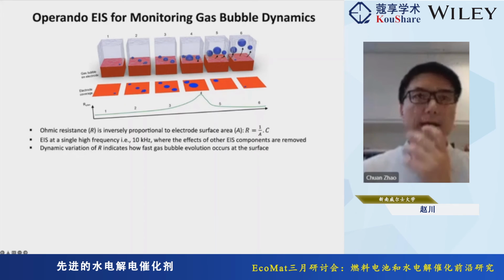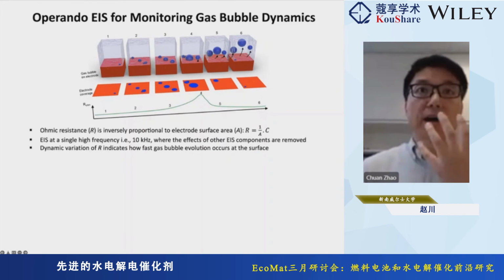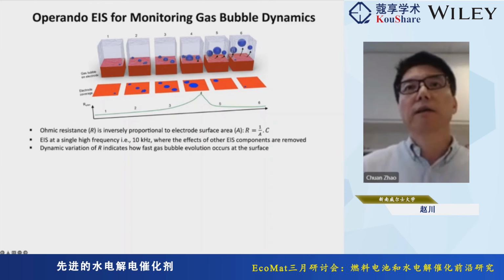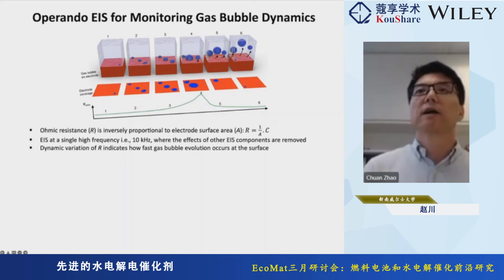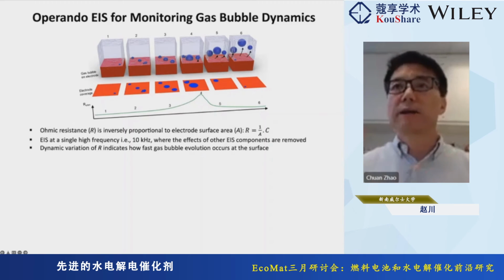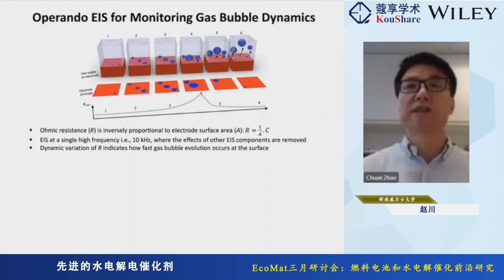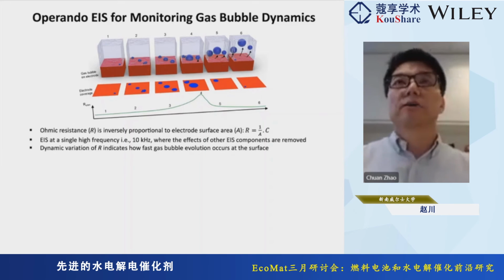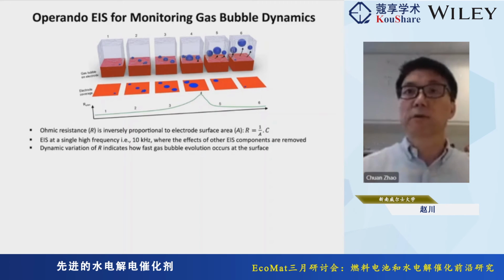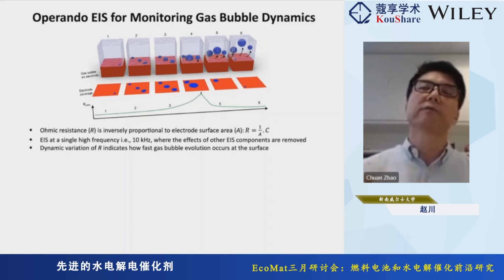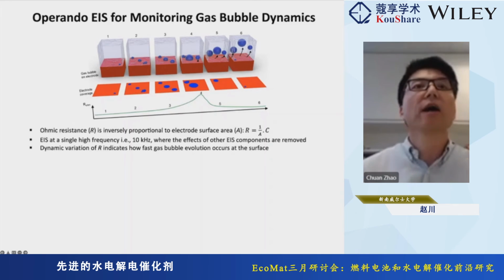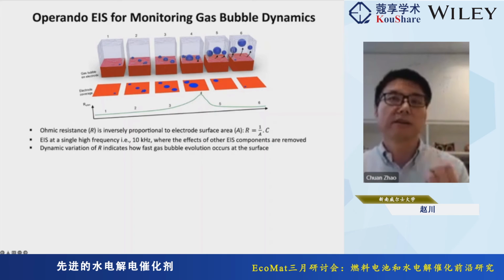And then we can record the EIS at a single high frequency, for example, 10 kilohertz, where the other EIS components, for example, the phase relaxation or the Faradaic charge transfer resistance, are all removed. So we get a higher sensitivity by monitoring the resistance change.